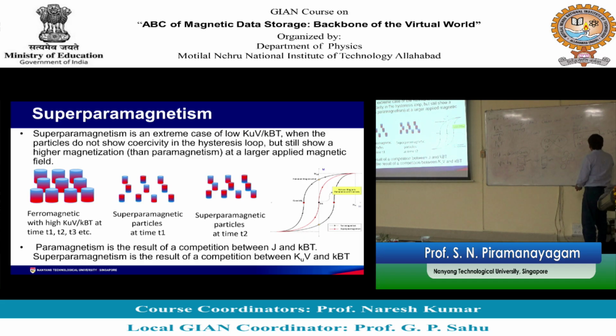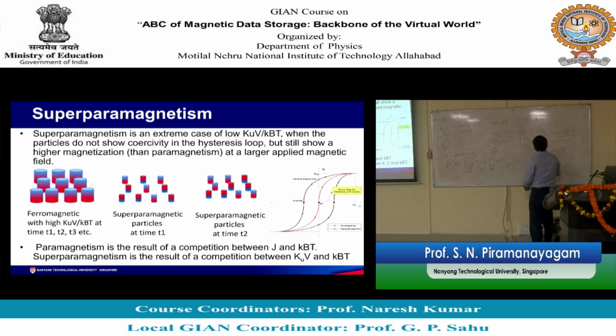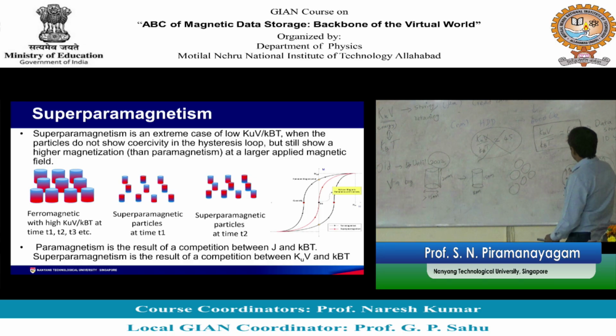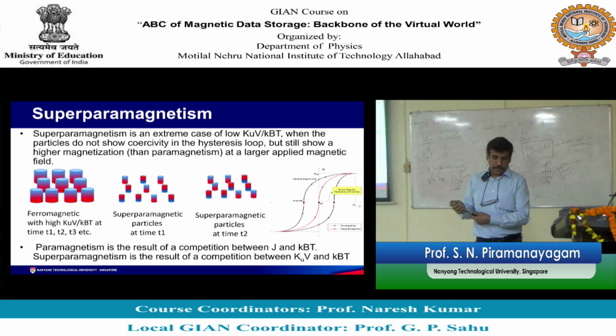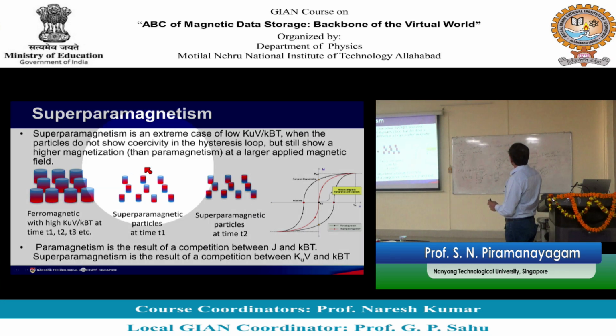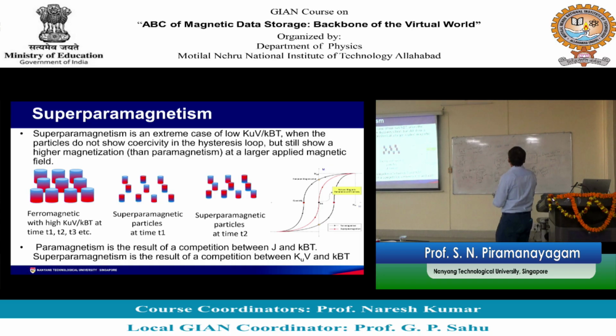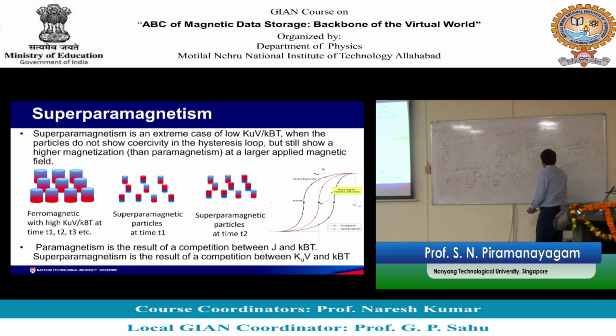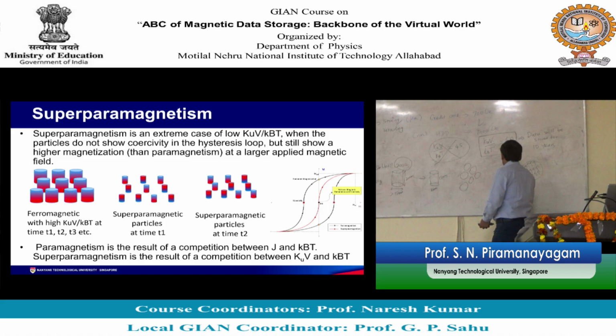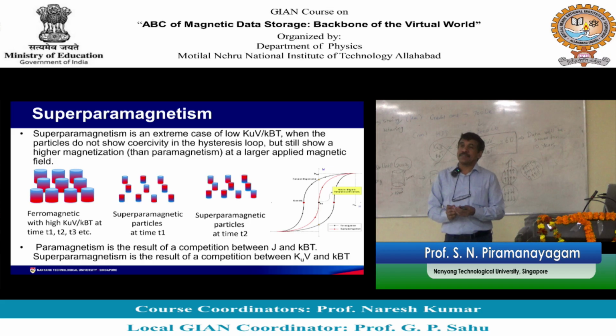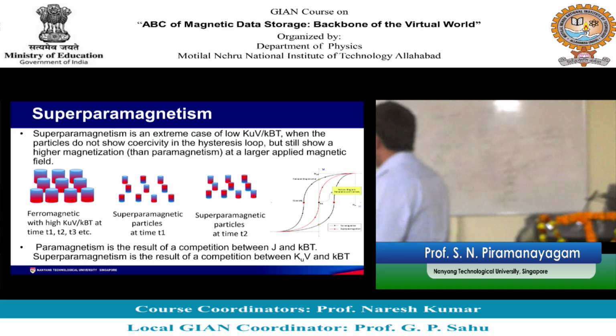The neighboring spins are always parallel, but as a collection. For example, let us say this is a small grain and I have another grain where again the spins are like this. So, when you have a collection of spins like this, the magnetization is in this direction, right. So, in superparamagnetism what happens is that as a collection of spins, their magnetization flips between up and down. Together they flip direction. So, the ferromagnetic property is still maintained, but as a collection the magnetization keeps fluctuating as a function of time.